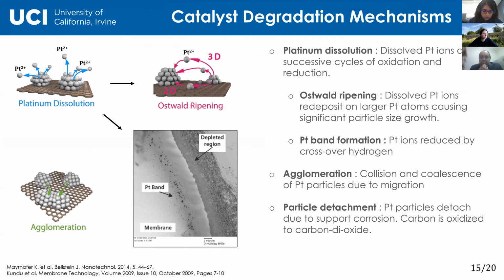I imagine we will see more platinum bands in wet conditions because that's where platinum mobility is higher. However, I'm not sure. I'm not aware if the effect of relative humidity on platinum band formation has been systematically studied. To us, platinum band is sometimes there, sometimes it's not there. We do SEM cross section and we see it's there. And what's interesting also is that XRF will capture this platinum. We'll say we didn't lose platinum loading because XRF detects all the platinum, but actually, this platinum is not active. So one has to be careful interpreting XRF results.